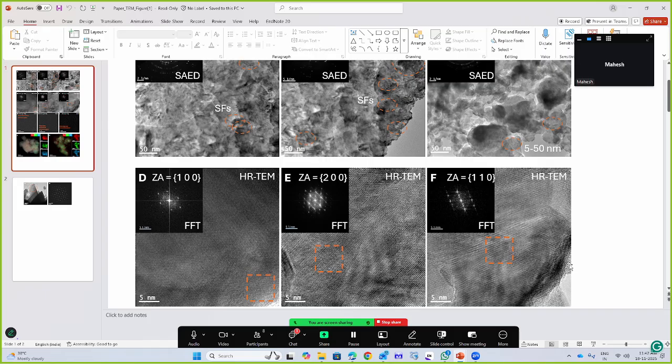First, one sample, we will see at high temperature. What is the melting temperature? Okay, 500, 600, where TGA. I think 450, 500. Not 600. Maybe it melts at 600 something. Then you need to go 100 less in SPS, because it's under pressure, right? Then 500. Try 500, 30 minutes, one sample. See whether the grain size changes and whether it deteriorates fully or is okay to improve the property.